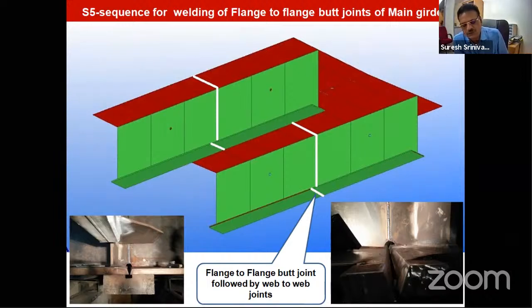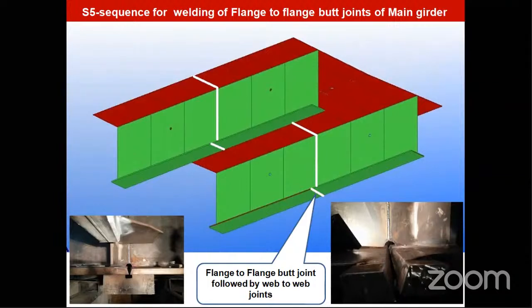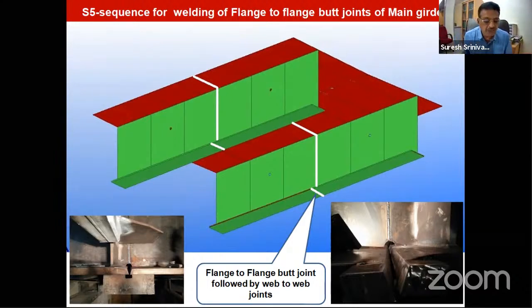And somehow they felt that overhead welding cannot produce a good quality weld. So what we had to do was, we went for a ceramic backing joint from the top side, the root welding. After welding this, we went about welding in a multi-pass joint. As you know, any single V butt weld will produce heavy distortion. And in fact, when we first welded this in the mock-up, we faced a problem of buckling of the web plate. So immediately we told the designers, and this buckling was avoided by putting extra stiffeners. The stress was caused by welding. That means compressive stresses were introduced due to the angular distortion on this web plate.